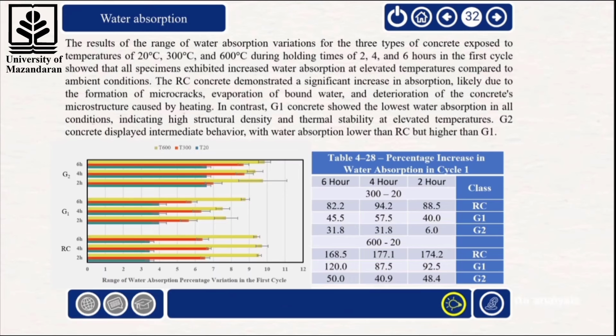The corresponding table shows the percentage increase in water absorption during the first cycle for the 3 types of concrete. The highest absorption was recorded for RC and the lowest for G2, while G1 showed intermediate performance. As the temperature increased from 300 to 600 degrees Celsius, all values rose further, with RC consistently exhibiting the highest absorption.